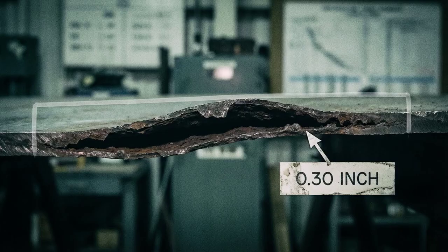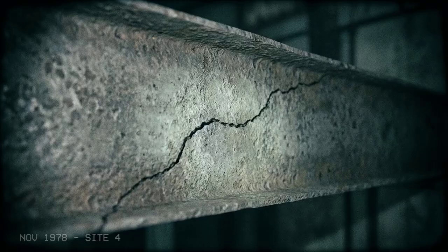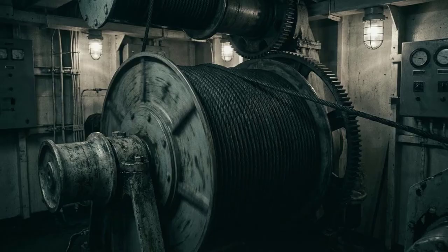If lifted faster than 3 feet per minute, dynamic stress will exceed the embrittled steel's fracture toughness, and the hull will tear along rusted seams. The wreck is not a solid object anymore. It is a collection of corroded fragments held together by hope and hydraulic pressure. The corroded hull cannot tolerate rapid acceleration. Lifting faster than 3 feet per minute would induce dynamic stress that exceeds the fracture toughness of the embrittled steel.